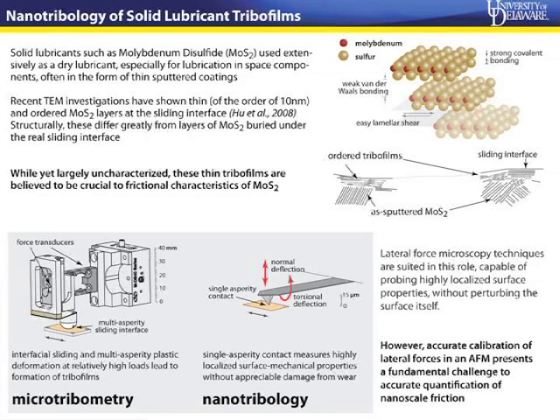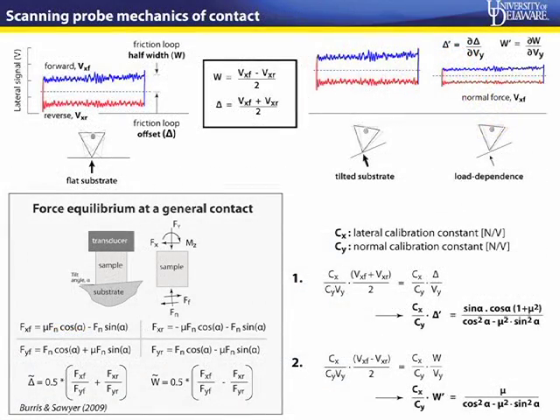It's not very different as a tribometer from your conventional micro and macro scale tribometers, in the sense that you have a load cell, you have a pin on a sliding contact. Here, the load cell is essentially made up by a laser source which reflects on the back of the cantilever and goes on to the PSD. One of the main challenges of lateral force microscopy, as it's called, is calibration. How do you go from the raw signal in volts to actual quantitative friction measurements at the interface in nanonewtons or micronewtons?